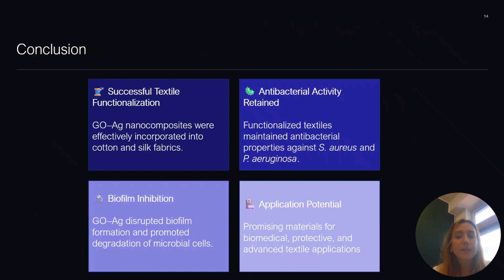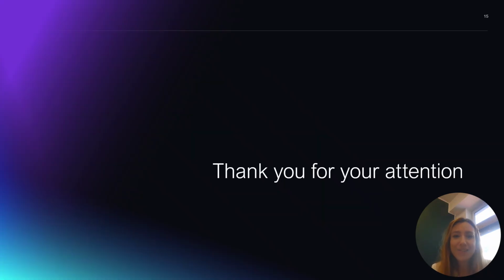In summary, we successfully developed nanocomposite-coated cotton and silk fabrics with antibacterial and antibiofilm properties. The nanocomposite was stably incorporated into the textile structure, remaining attached even under mechanical stress and simulated breathing conditions. Moreover, both materials demonstrated satisfactory antibacterial activity against Staphylococcus aureus and Pseudomonas aeruginosa, highlighting their potential for biomedical and protective textile applications. And thank you for your attention.